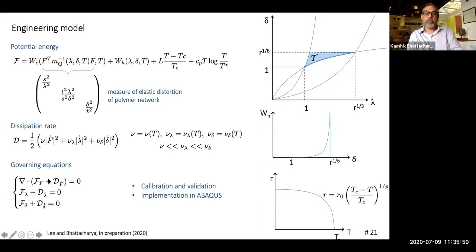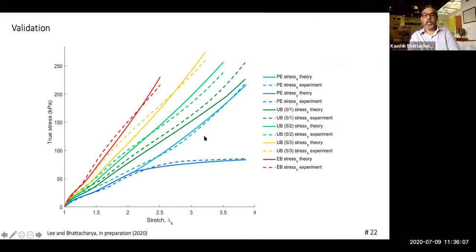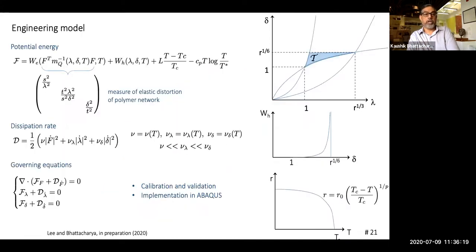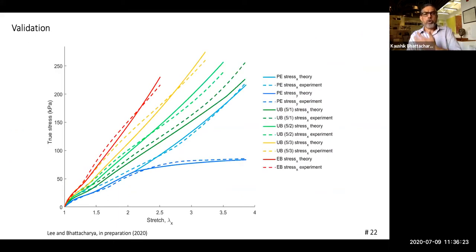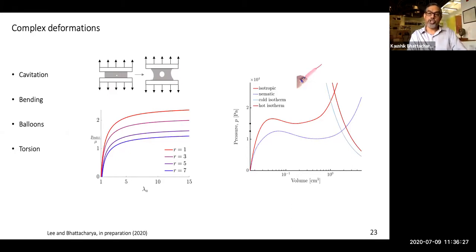You can calibrate these with experiments on macroscopic specimens, implement them in commercial finite element codes, and here's the validation. The solid lines are the behavior of the model, and the dashed lines are the behavior of the calibrating experiments. All these experiments are really calibrating only about 9 constants. So you can do complicated engineering calculations now with all this complicated behavior built into it. And one of the things that you can study is a lot of different structural instabilities, including cavitation, a balloon instability, torsional instability. And in all of these, you see this very interesting combination of material instability manifested by microstructure and structural instabilities that we know in structures.